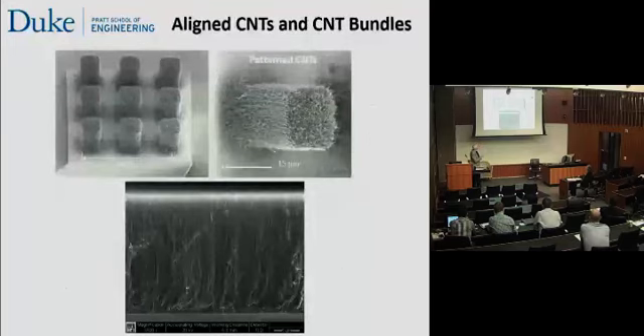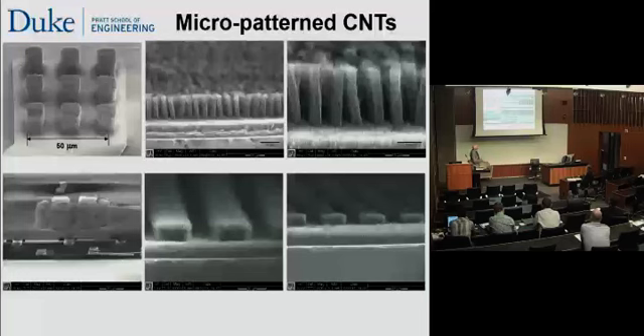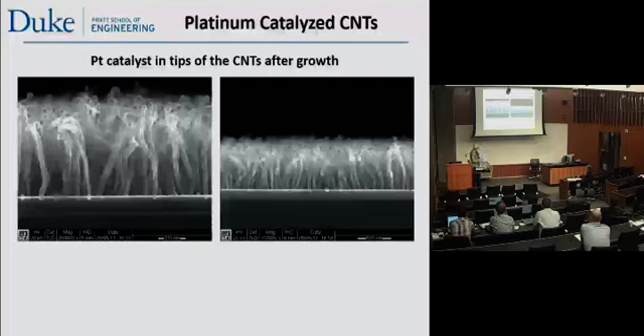We can also grow these in all kinds of neat patterns. This is a forest of those carbon nanotubes that you saw, and these are bundles of forests, so they're full of these, millions of these small carbon nanotubes that I just showed. And we can also pattern them in various ways. We have bases of nanotubes with these pillars sticking up, and that gives us a different type of interaction with an electrolyte or with an analyte than other structures. So we're in the process of really engineering that structure to be optimized for electrolyte interactions. And one strange structure we can grow is a platinum-based catalyst at the tips of all these nanotubes. So you see these nanotubes are a little different than the nanotubes we showed a minute ago, but what's unique about them mostly is that they have this platinum nanoparticle in the tip.